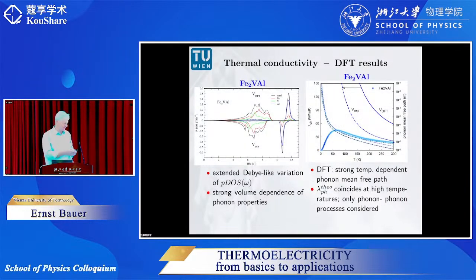And again, when using these phonons, as shown on the previous page, we can account for the temperature-dependent thermal conductivity. The measured thermal conductivity is plotted here, and these solid and dashed lines are calculations under certain assumptions. What one can see is that at least at high temperatures, the phonon thermal conductivity can be nicely calculated from DFT-based modeling. At low temperatures, however, we are far away from the reality of our measurements. Okay, at this point, we can make a short stop.